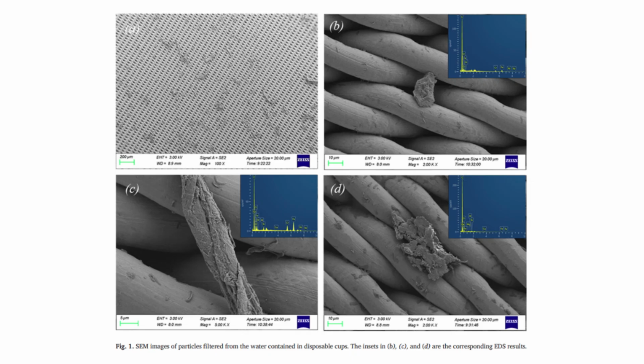The cups were filled with ultra-pure water at 95 degrees Celsius, so 203 degrees Fahrenheit, and then covered with stainless steel lids and allowed to sit for 20 minutes. They also repeated this process at 10, 40, and 70 degrees Celsius. After that, the water was filtered through a 1 micrometer steel filter membrane to collect the particles. The filter membrane was then carefully removed and analyzed. The particles filtered from the paper cup water were observed with scanning electron microscopy, and the micrographs are shown in Figure 1. Different shapes of microplastic particles can be clearly observed on the membrane.